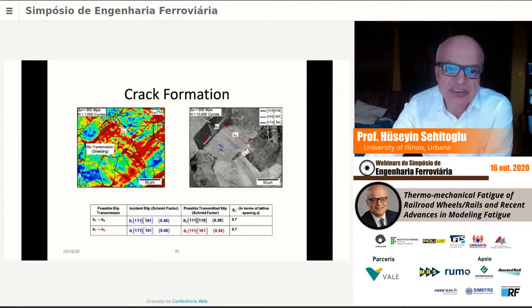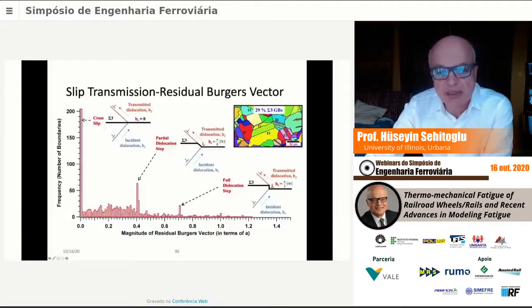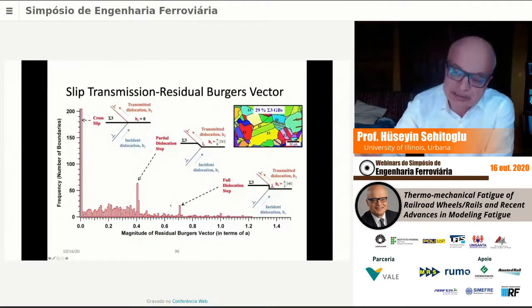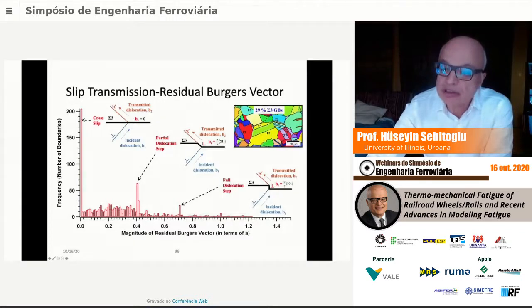You could see this in these strain images in digital image correlation, if your grains are large enough. So that would be the characteristic fatigue crack initiation. We need to predict that LC, so to speak. We call it the cluster size. And the boundaries are all over the place, right? There are different boundaries. You can map out all the residual Burgers vector at each boundary.